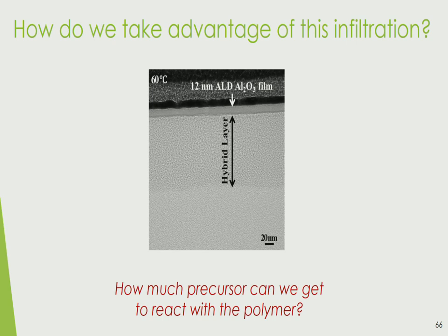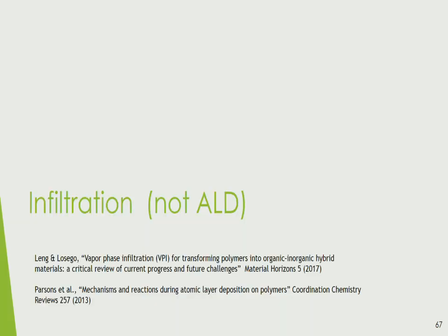That was actually the question that I asked a couple of my researchers in the group: number one, how can we manipulate this? But on a more fun level, how much precursor can we possibly get into this polymer? And it was pretty surprising. So this led us into infiltration and understanding infiltration mechanisms into polymers. And this is distinctly not ALD. The precursor gases are diffusing in, they're reacting, and then some of the products are diffusing out.